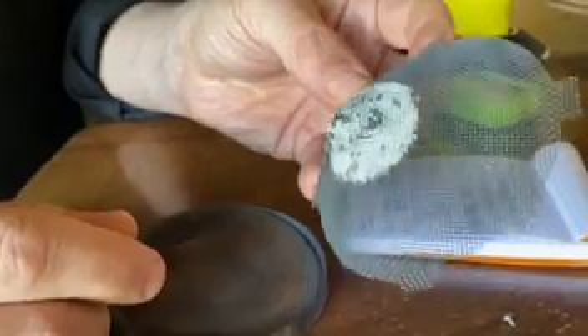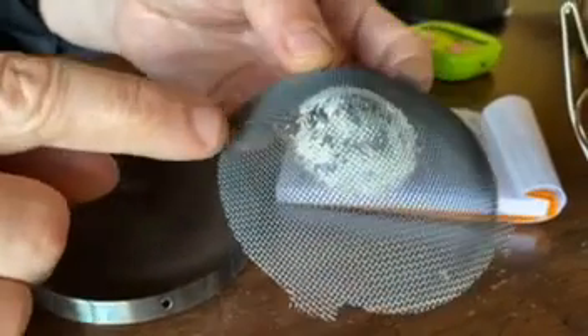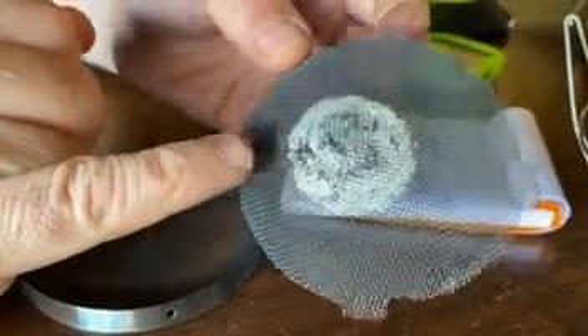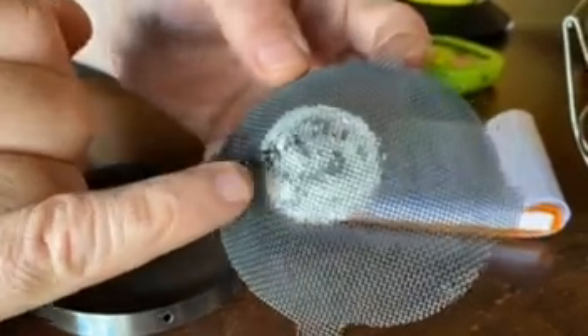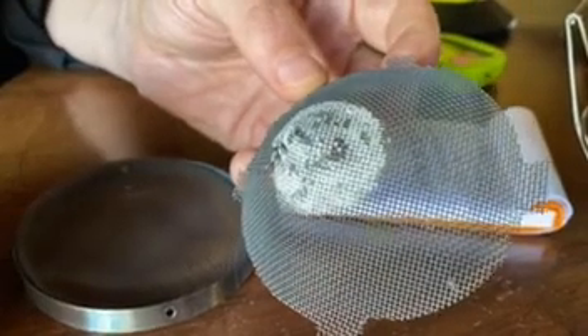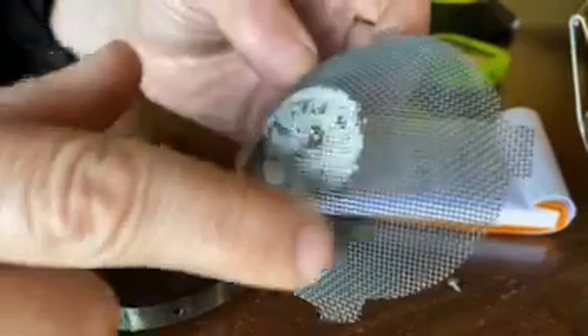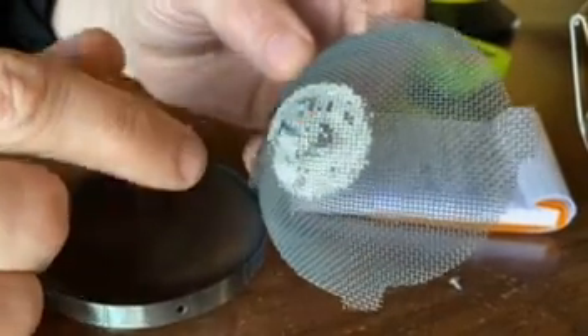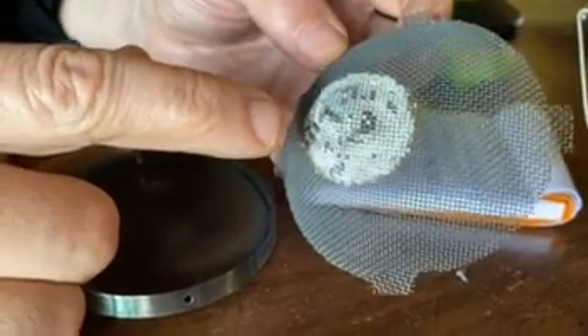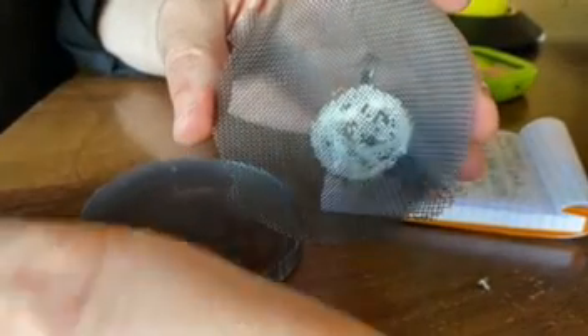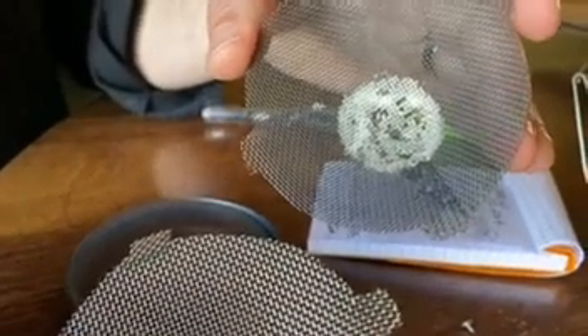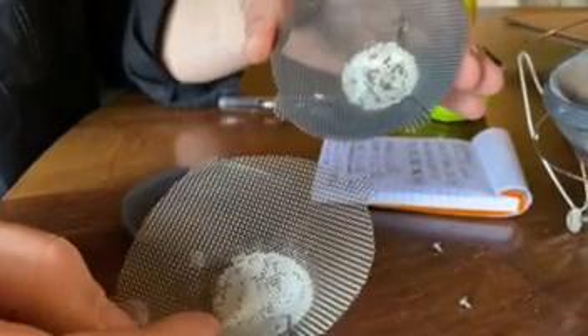Going on to the cone screen, you can see that there's almost, this was due to the initial welding. There's almost no damage to the internal screen. It's nicely oxidized here, and in the section where the ceramic was protecting it, it is in perfect shape. From the front side, you can see also that compared with the fresh sample, there's almost zero degradation and that it is in very good shape.